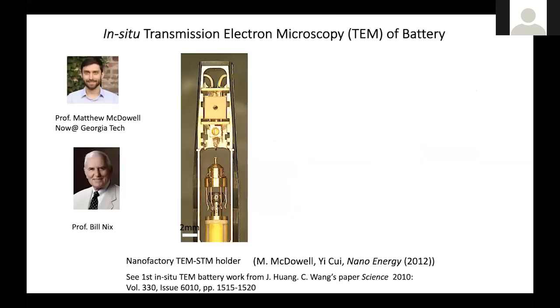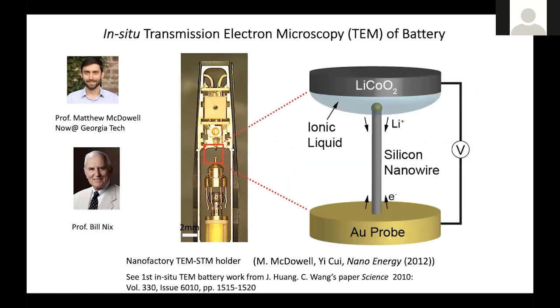What I want to share with you is that during this process of material design, we need new tools to look at how the batteries work. We were one of the earliest groups to adopt in situ TEM of electrochemical cells, and to build a single nanostructure battery inside the TEM. In this TEM holder, we can mount a silicon nanowire, plug it into the ionic liquid, and lithium cobalt oxide is the cathode. Now you can cycle this battery by applying electrical current. Electrons come in, lithium diffuses into the nanowire, charge is neutralized with the electrons, and starts to react with silicon.